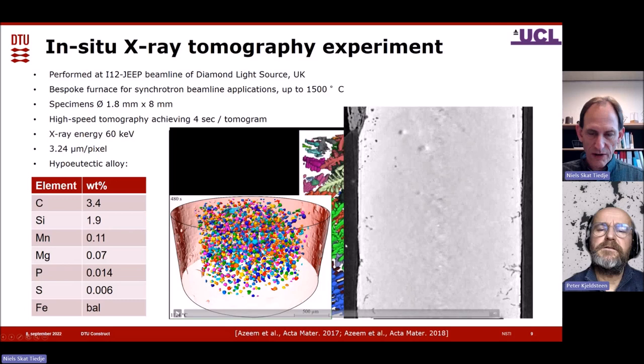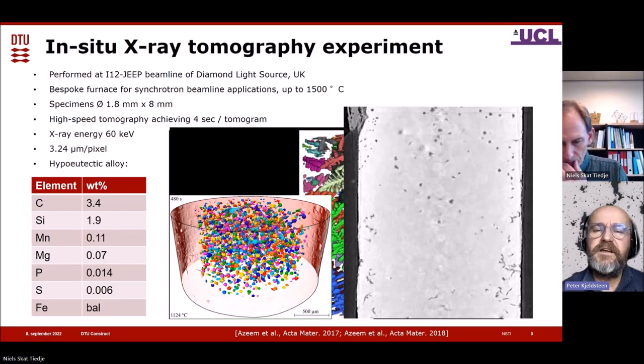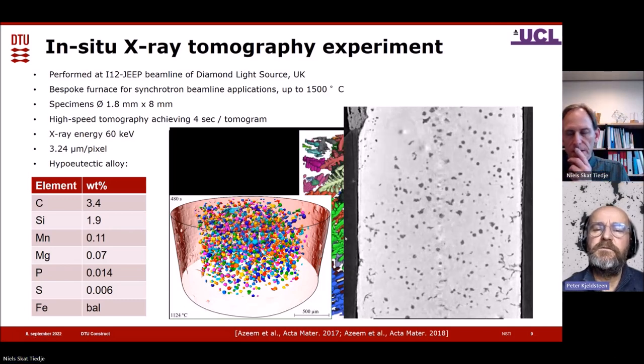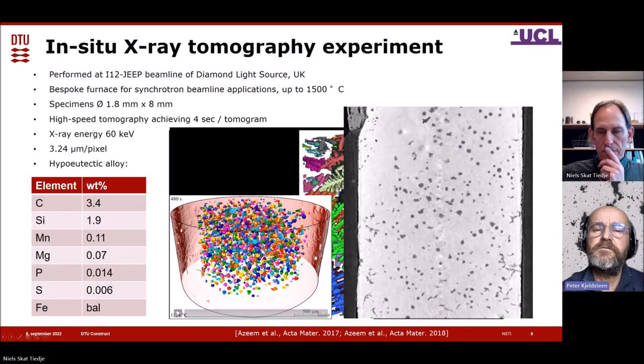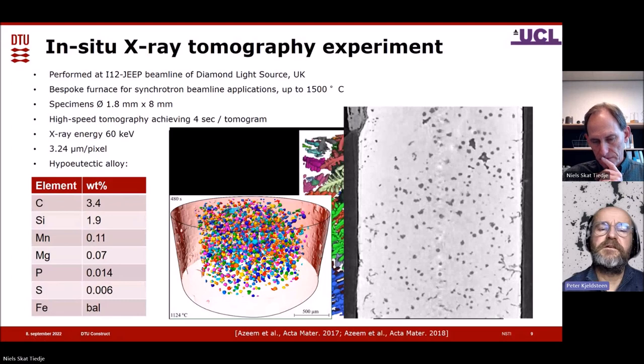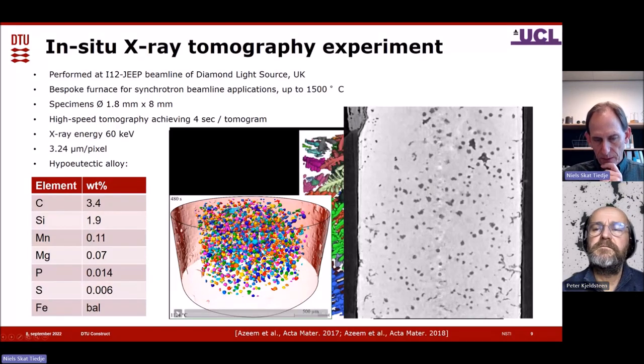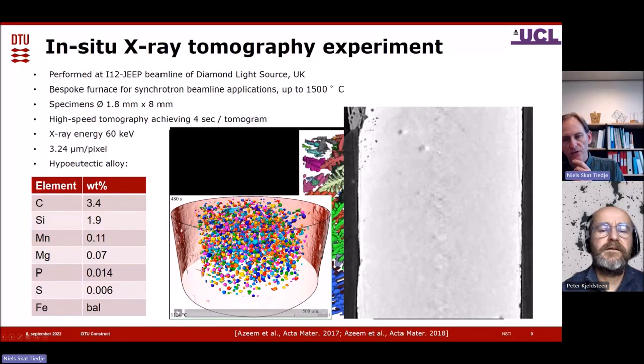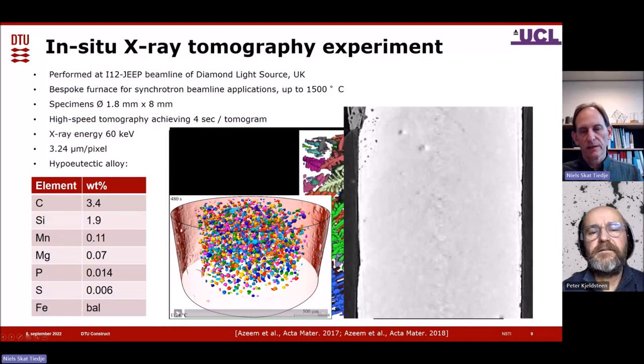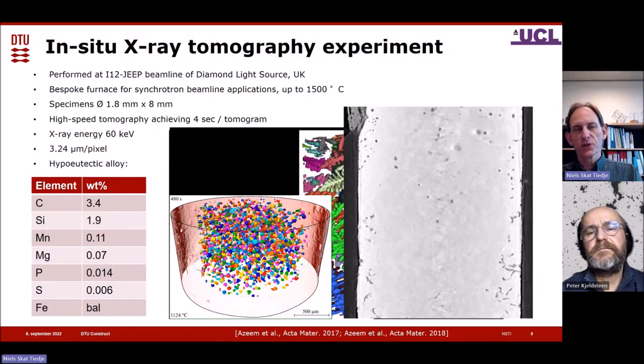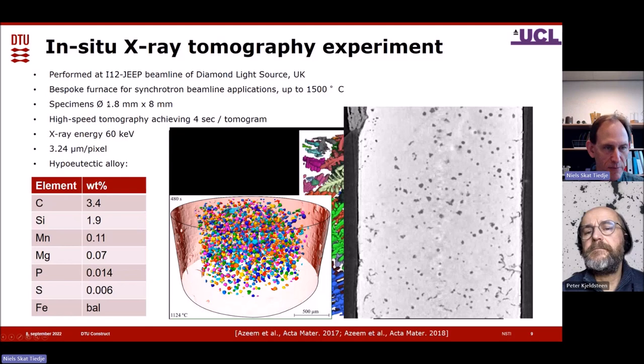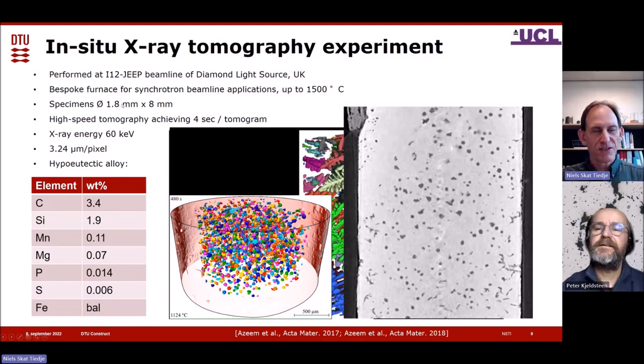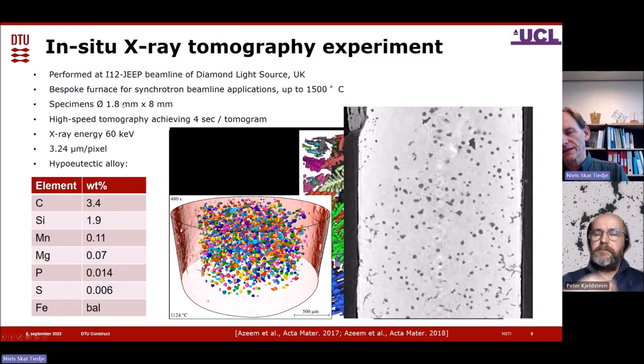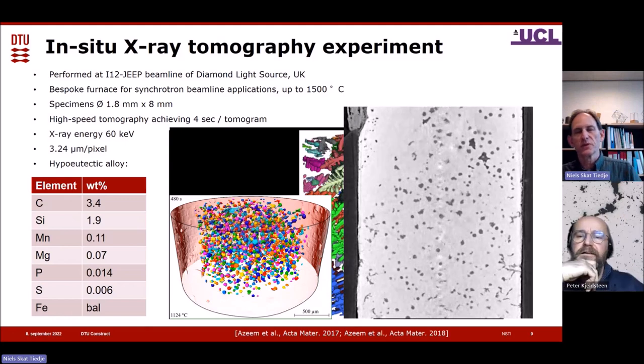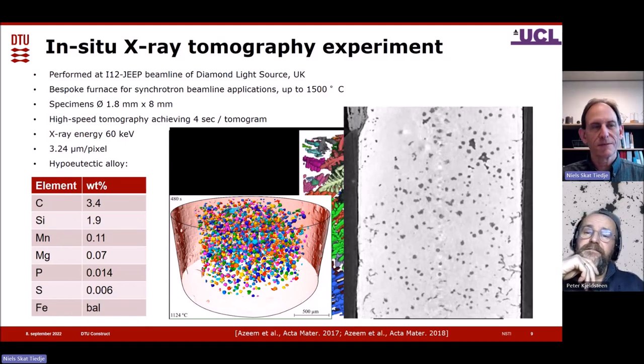So yeah, good fun. Here the dendrites you see in the back were formed first, and then afterwards the graphite grew. In this case we cannot show the dendrites simply because of the size of the sample. It sounds stupid, but we have a 1.8 millimeter, maybe 2 millimeter sample, and that is so thick that we are not able to differentiate the dendrites from the melt.